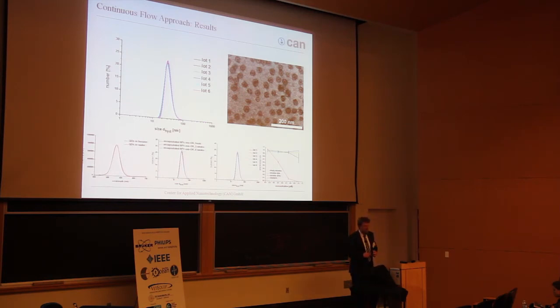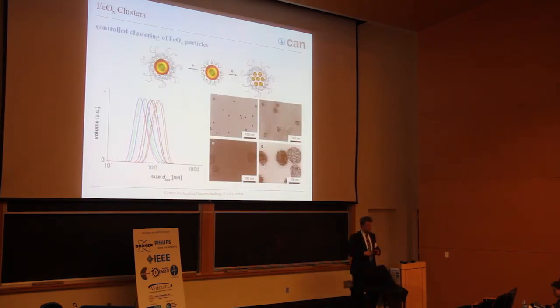So we had the question, is it possible to change the system to yield clustered particles in the micelle? And yes, it is. So we tried it with iron oxide particles, and what we did is we changed the polymer to particle ratio, and this is very important, we changed the mixing behavior too.